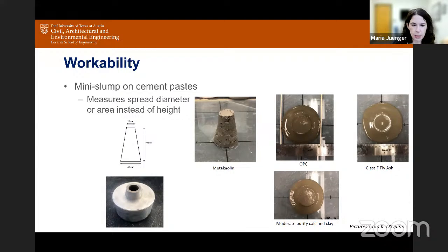So when we talk about workability, this is a good imaging graphic demonstration of what metakaolin does to the workability of a concrete mixture. This is actually a mini slump test on pastes. It's not a concrete mixture, where the mini slump cone diameter is 40 millimeters at the bottom, and the height of the cone is 60 millimeters.